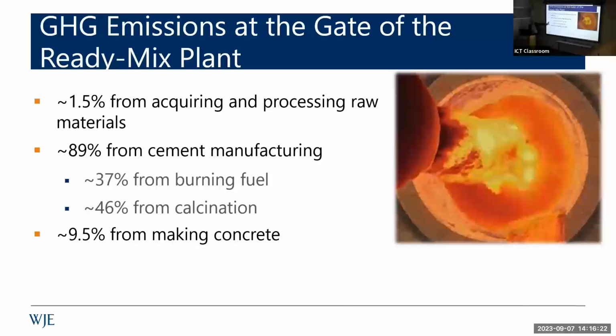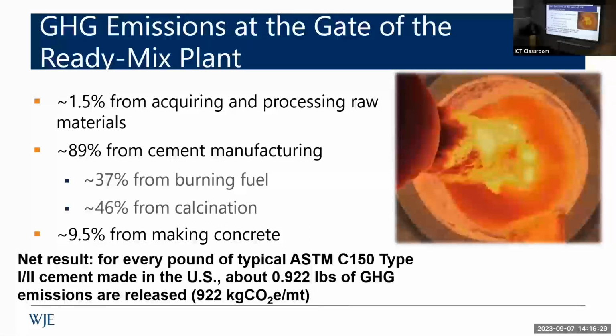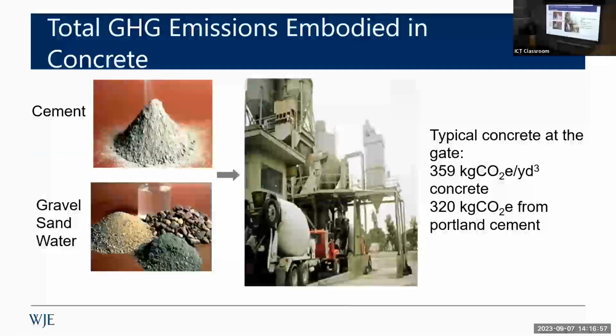And ultimately, that's going to have to be captured. They're going to have to capture that and do something useful with it. Roughly in the US, for every pound, kilogram, metric ton of cement that we manufacture or sell, I should say, roughly 0.922 pounds, kilograms, metric tons of CO2 is produced. And so you hear people say for every ton of cement, there's a ton of CO2. That's pretty good, not a bad estimate. A little bit less, we're getting better, but that's the reality. So that's what we're confronted with.